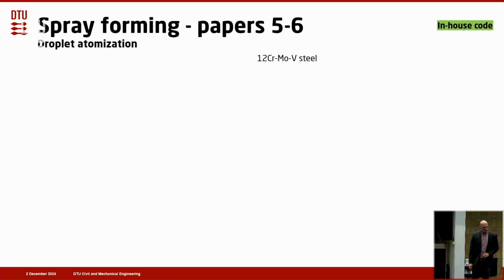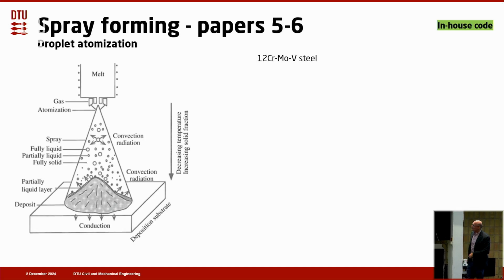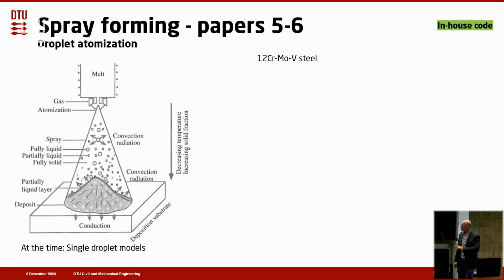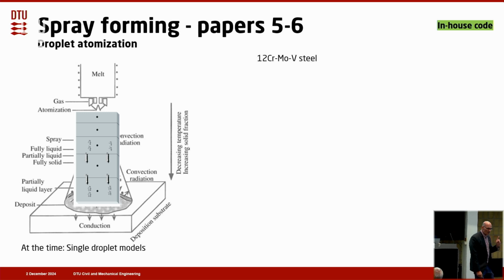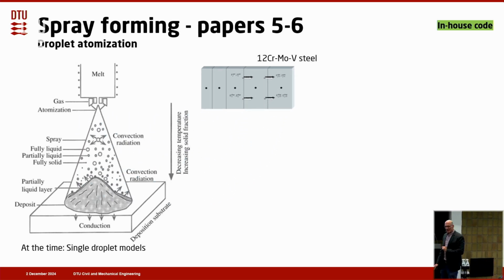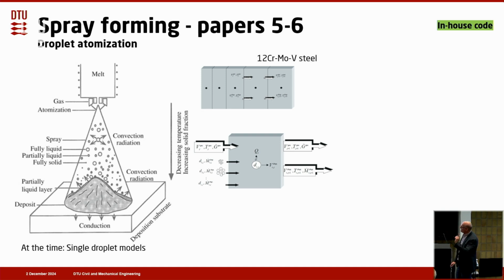So the next process was spray forming. Now, spray forming is a process where you have a melt, it's atomized, you get a lot of droplets, and then you build a billet. Now, when we made these models, there were only single droplet models in literature. So what we proposed was a one-dimensional model. You see that here.